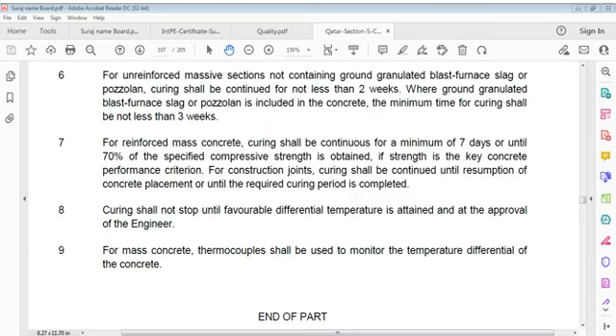For reinforced mass concrete, curing shall be continuous for a minimum of 7 days until 70% of specified compressive strength is obtained. If strength is a key concrete performance criterion for construction joints, curing shall be continued until resumption of concrete placement or until the required curing period is completed. Curing shall not stop until a favorable differential temperature is attained, and at approval of the engineer. For mass concrete, thermocouples shall be used.